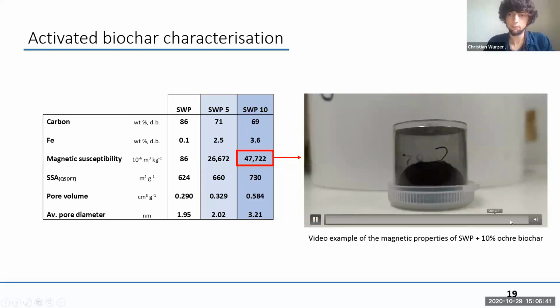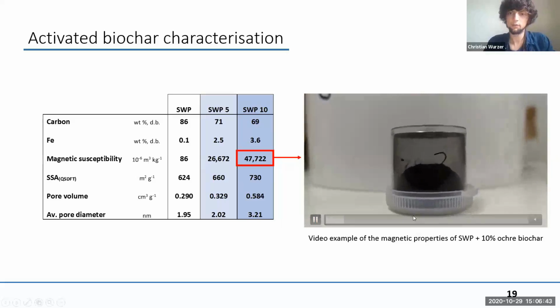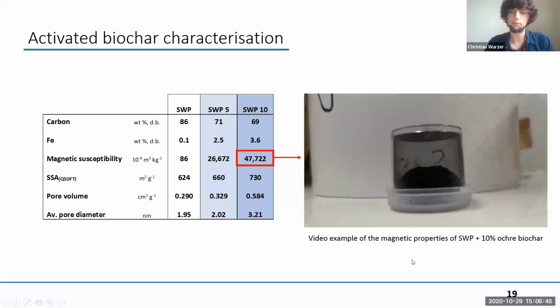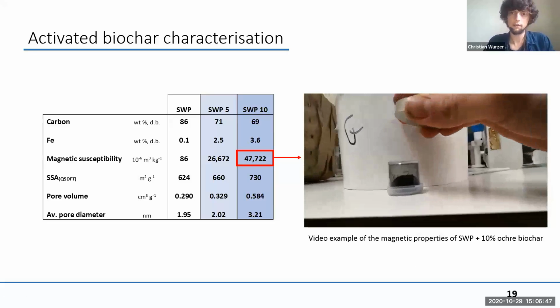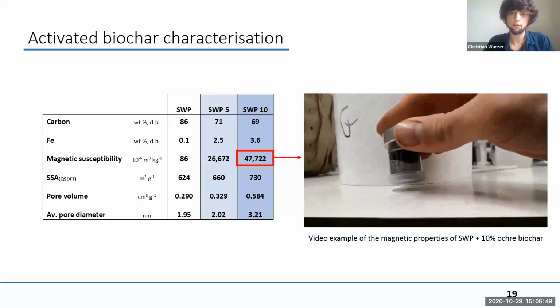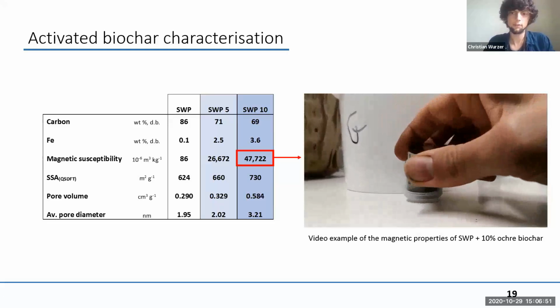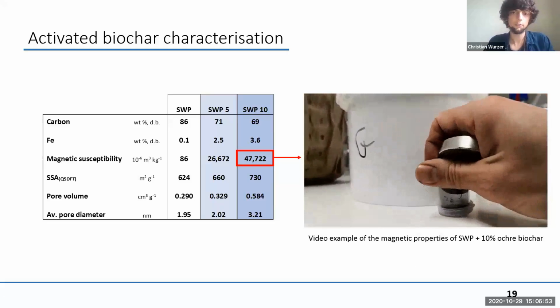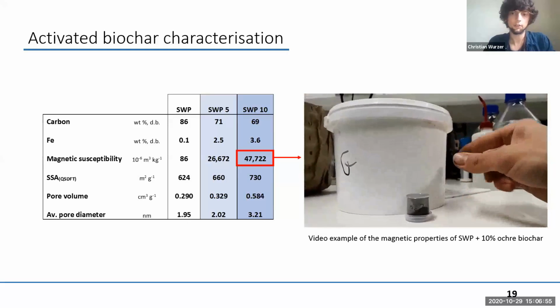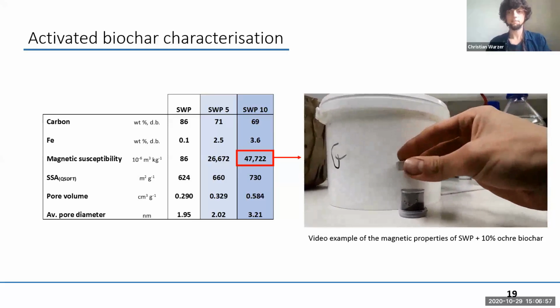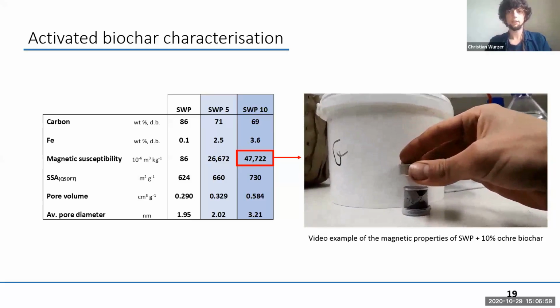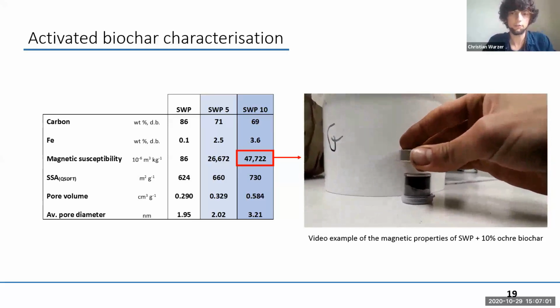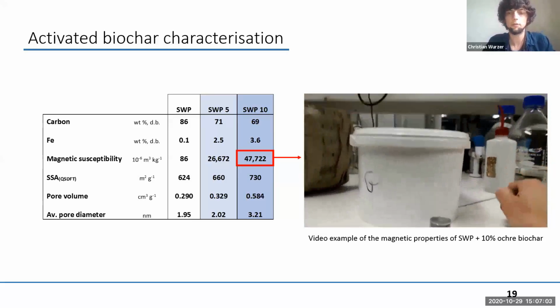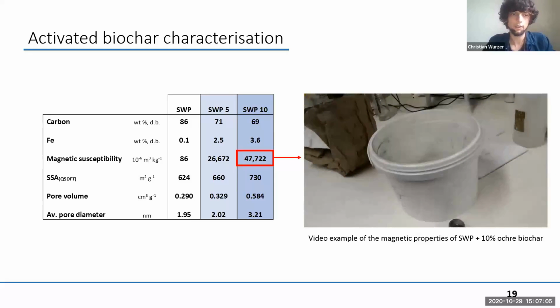And to give you an example, here is our softwood pellet with 10% ochre addition, and my dirty hands will put a magnet next to it, and you can directly see it is quite magnetic, so it's not easy to actually get the magnet off again. And that also works in the liquid phase. So the magnetic susceptibility is high enough to actually use this biochar for magnetic separation.